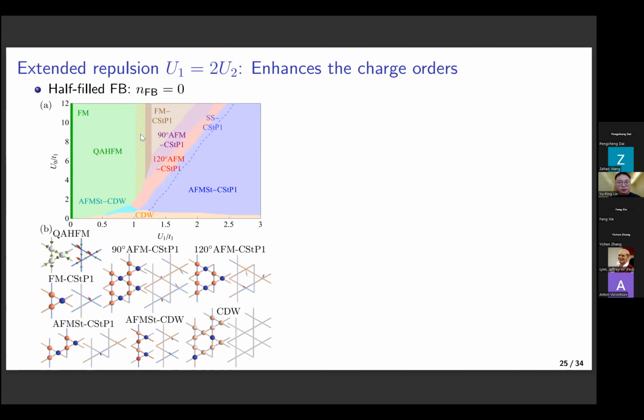And if we further increase the extended repulsion, we can see some charge stripe. And if we increase it further, we can see the 90-degree antiferromagnetism, 120-degree AFM, and also some other different interesting orders.